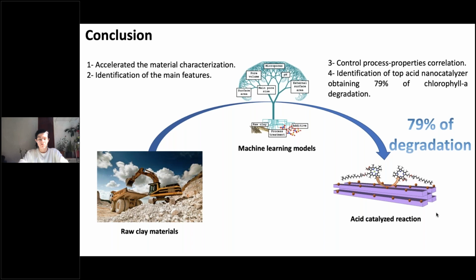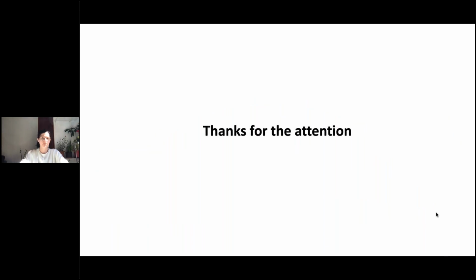So in conclusions, we have demonstrated an accelerated approach for characterization and development of processed nanoporous materials. We identified through feature importance analysis of the models the main features affecting the properties of processed materials. Each investigated clay-based material reveals a unique behavior which is affected by structural defects and ion substitutions. We control the process-properties correlation, and we identified the top acid nanocatalyst, obtaining 79% of chlorophyll A degradation. Thanks for the attention.